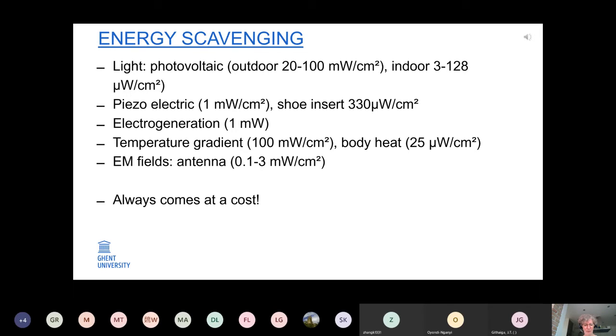Temperature gradient, we just listened to a presentation just before this. Body heat is reported to have an output of around 25 microwatts per square centimeter. But of course here the temperature difference is much lower than what has been reported in the previous presentation. There they spoke about a temperature difference of between 40 and 50 Kelvin, whereas when you use body heat, this would be around 10 Kelvin. And then also antennas from electromagnetic fields, around 1 milliwatt per square centimeter.